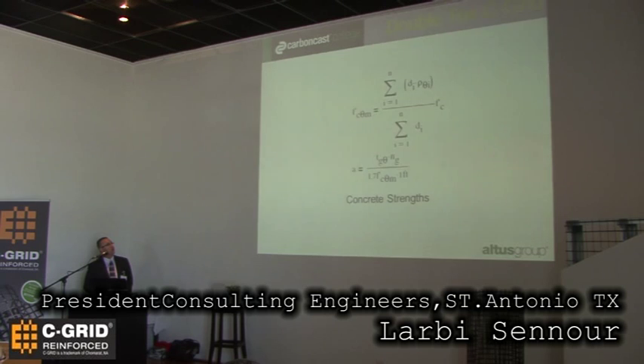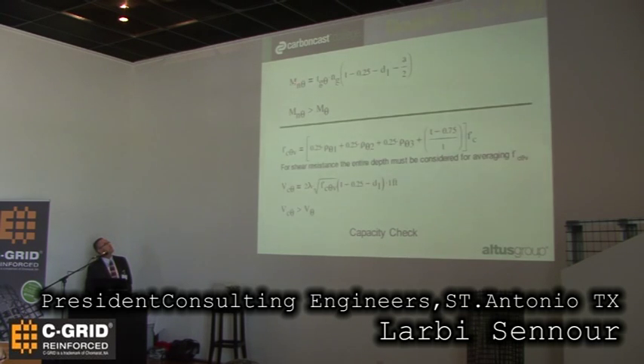Come up with your stress block, and then you calculate your moment. So your capacity of your moment is in the capacity of the grid reduced by fire times the number of grid you have times your D, which is the moment arm. And then you make sure that your capacity under fire should be greater than your demand under fire. That is a typical prescriptive method, and we have publications you can use. Or you can use our tests also. The same thing for shear. You do the same thing for shear.